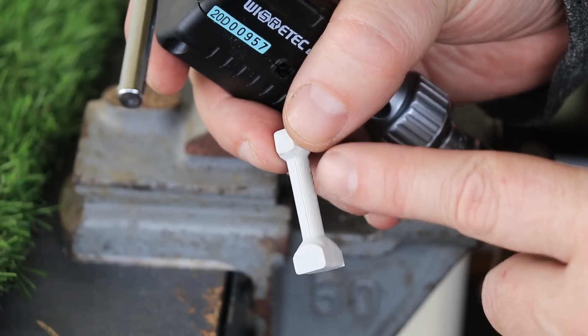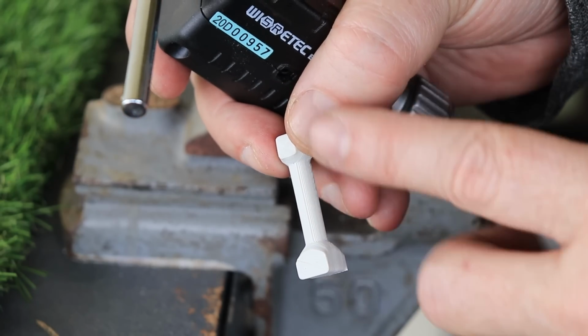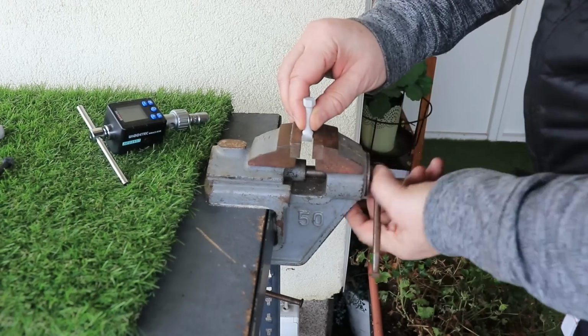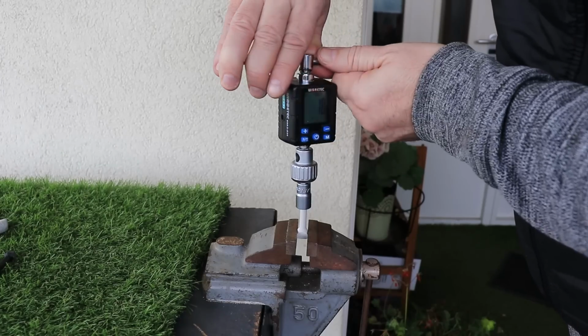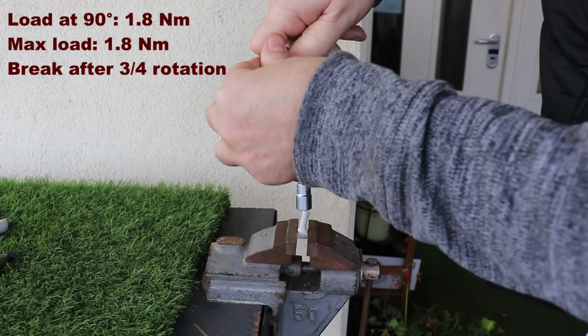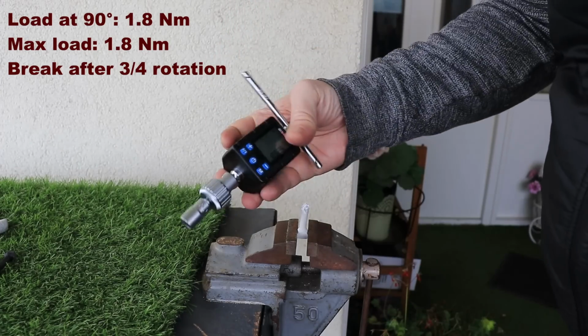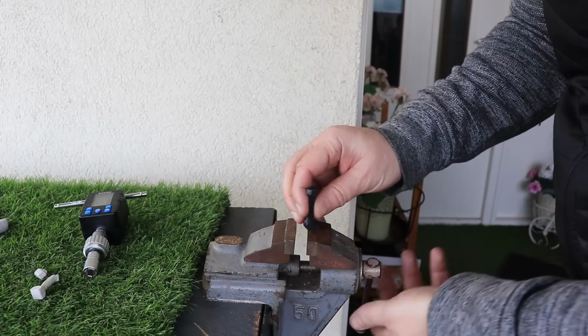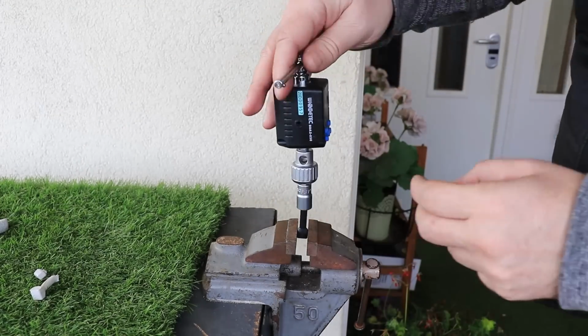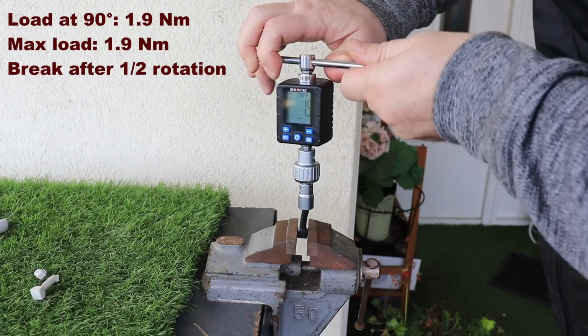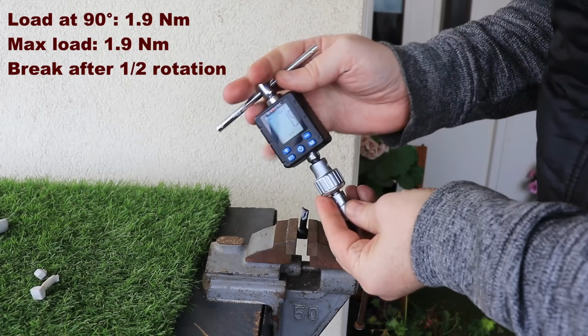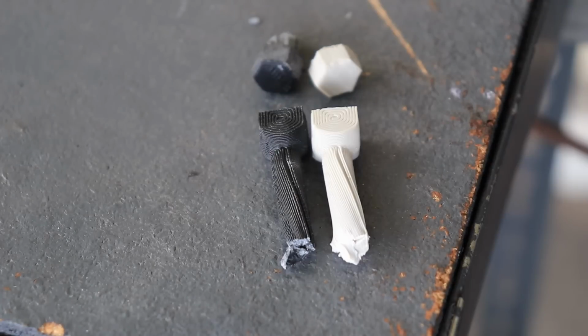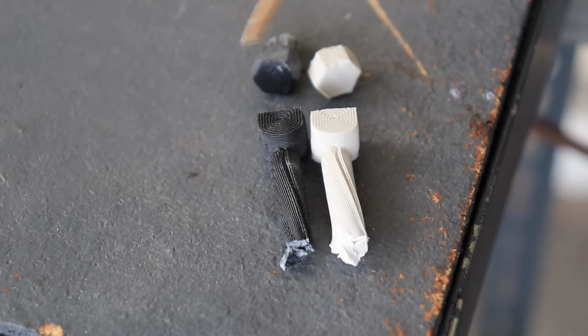Torque or twist test, I want to measure the load at 90-degree rotation and the maximal load. For ASA, 1.8 was the peak. Carbon fiber version, the peak 1.9. After the break they look very similar, and for the filling they were also very similar.